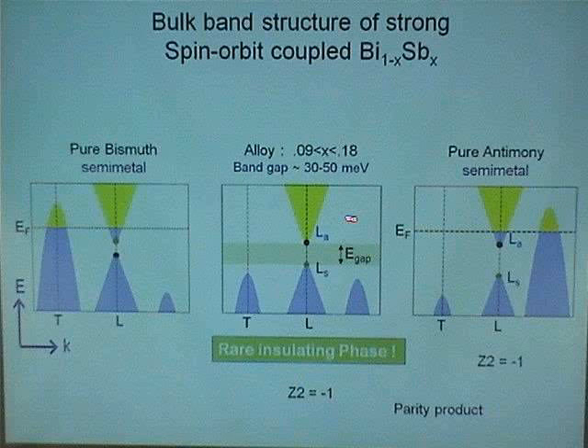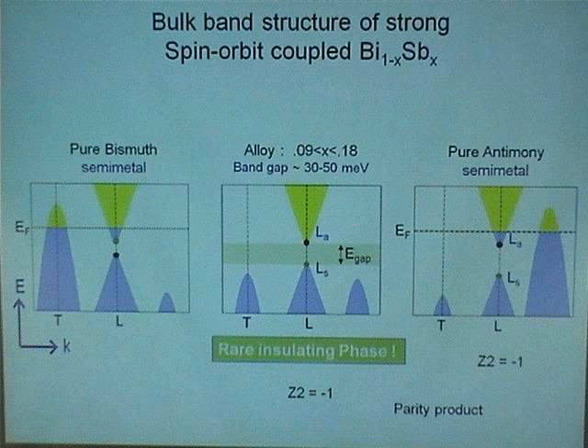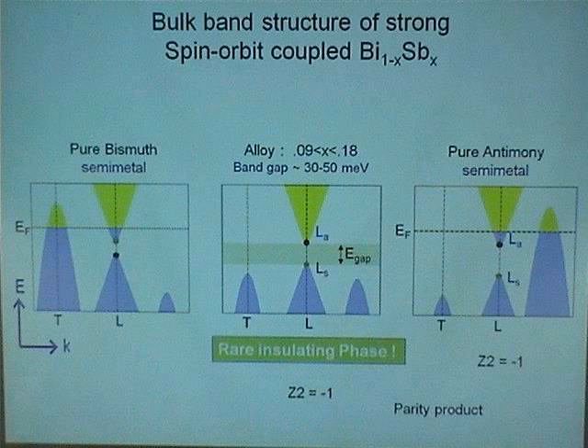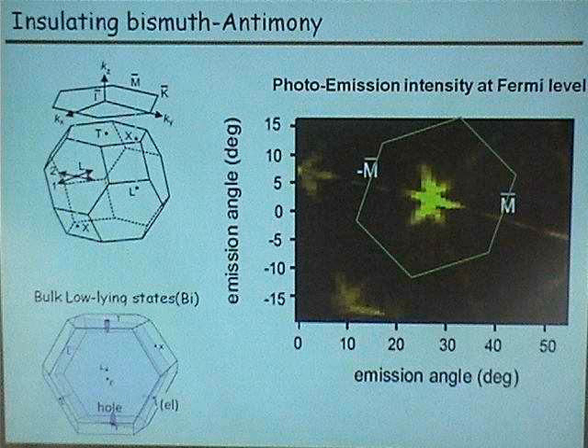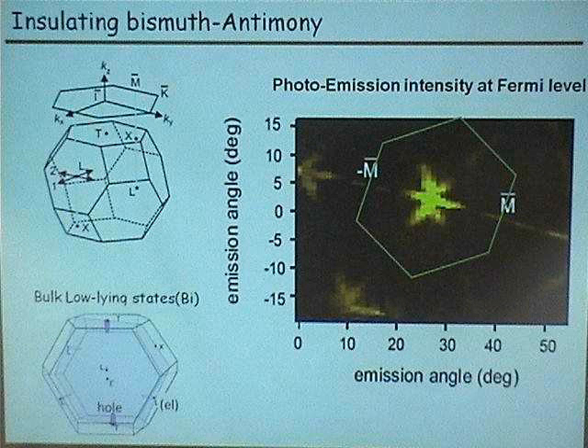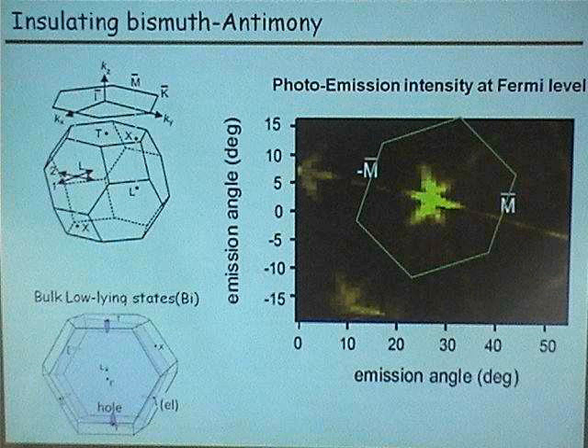If we cleave the surface of bismuth antimony, this insulating state is realized only at 9%, so your main matrix is still long-range-order bismuth. Although these are alloys, the XRD peaks are less than 0.01 degrees, so they are long-range-order, high-quality crystals. Nine out of 100 bismuth atoms replaced — it's a site disorder, not positional — and it turns out to be extremely insignificant. It does not destroy translational invariance, so K is a good quantum number in this alloy.